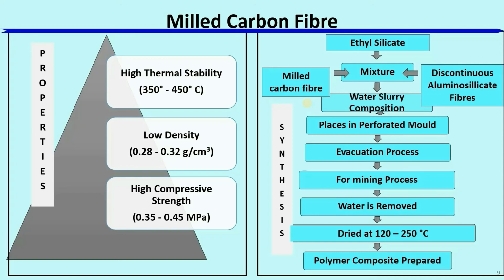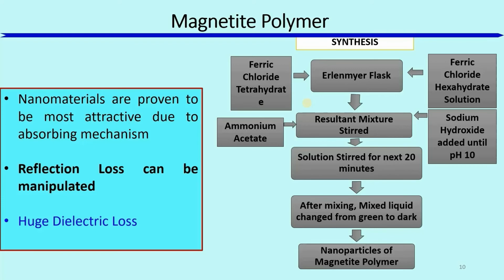Milled carbon fiber polymer is prepared by a mixture prepared using ethyl silicate, mild carbon fiber, and discontinuous aluminum silicate fiber. After mixing, a water slurry composition is prepared and it is placed in a perforated mold. After performing evacuation and forming process, water is removed and it is dried at 120 to 250 degrees Celsius. And after this, the polymer composite is prepared.